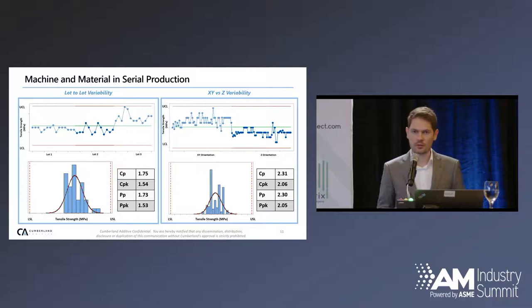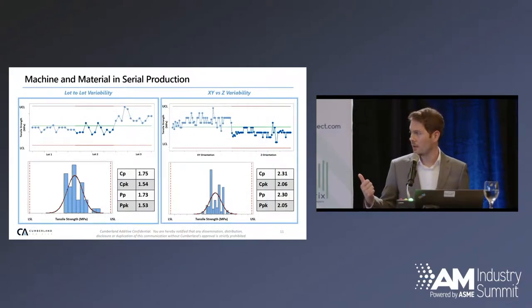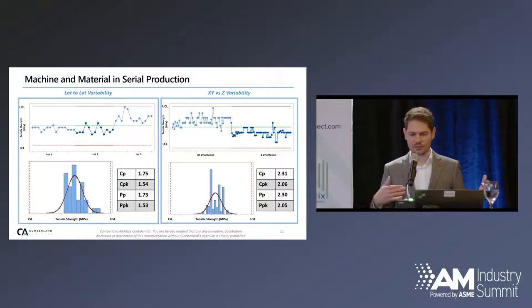Lot-to-lot variability: there are variations in material lot. We get material testing reports from all of our vendors, but there is a possibility that something happens that we're not testing for. We test for that to see — that's a big indicator of mechanical performance on the back end too. In terms of weighing risks: test the powder lots on the front end to ensure your feedstock input is good, and then on the back end do tensile testing so you know the actual part integrity is good. A question that comes up often is how is your mechanical performance in different directions — X/Y versus Z orientation. There is clearly an appreciable difference. The key is whether that difference is enough that you want to test X, Y, and Z specimens in every production build, or can you accept less than 5% variation and only test Z — minimizing testing costs from six bars down to one or two.